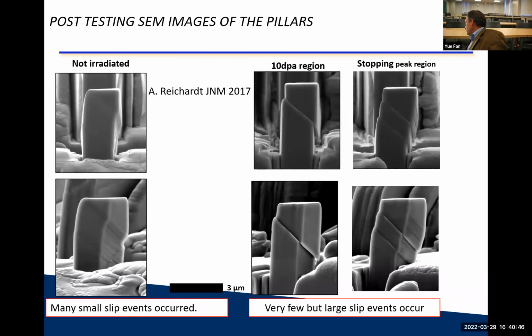So we look at not irradiated. In the not irradiated case, we see many slips, all parallel, of course, since it's in the same crystal. But in the 10 dPa region, maybe one, maybe two of these things. And all the deformation happens only there. It's one clear shear. In the stopping peak region, we see a little bit of both, but our stopping peak is 1 micron wide, and the rest of the pillar is like 2-3 microns wide. So it mixes both. Unfortunately, it's not that localized.